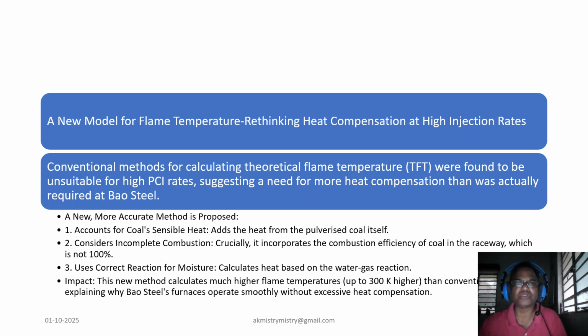When injecting coal, you need to add extra heat, and operators traditionally rely on a calculated value called theoretical flame temperature, or TFT, to guide this. However, at high PCI rates, conventional methods for calculating TFT were found to be unsuitable. At Baosteel, these older models suggested the furnaces were running colder than they actually were, implying a need for more heat than was being used for their smooth operation. This led to the development of a new, more accurate method for calculating flame temperature.